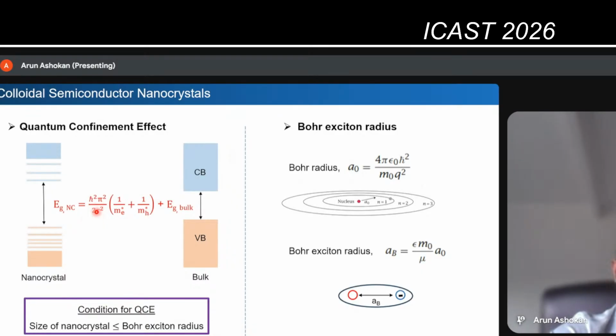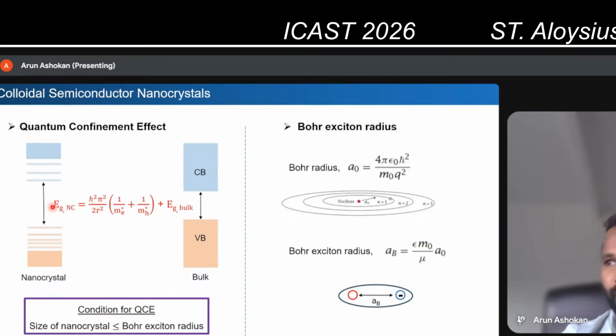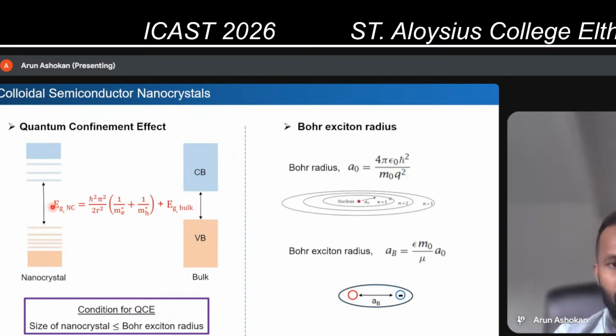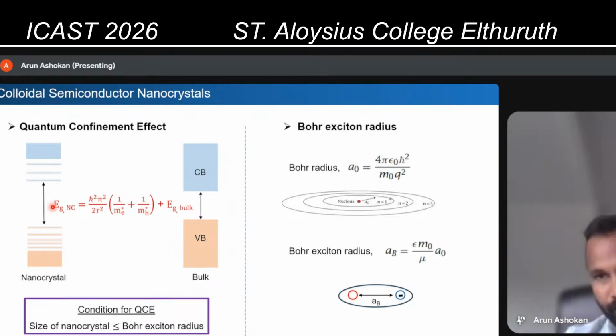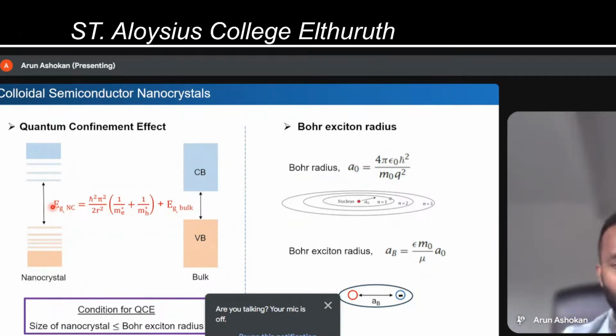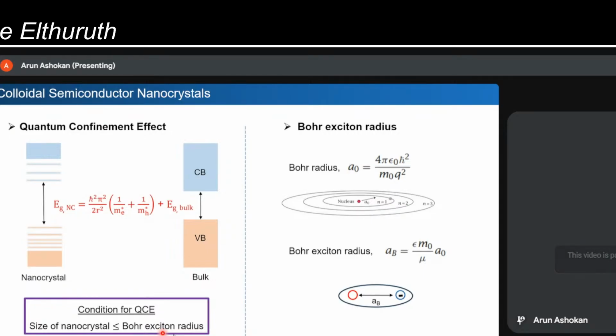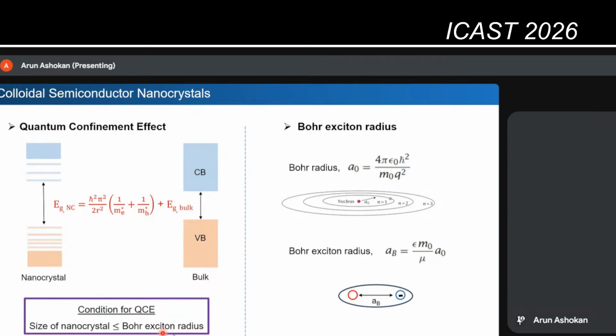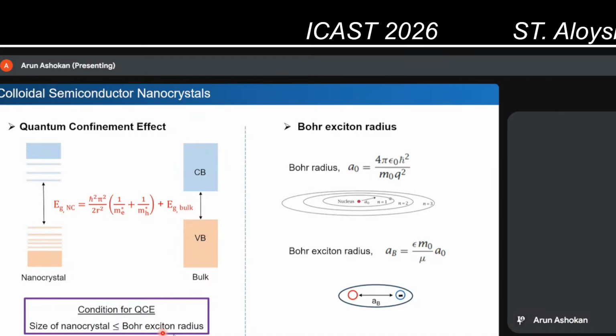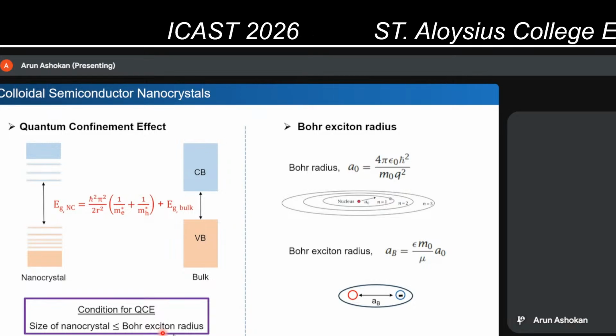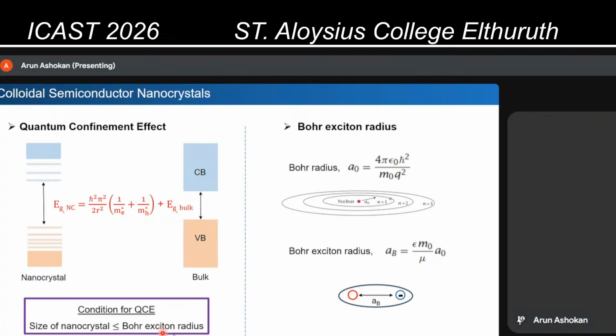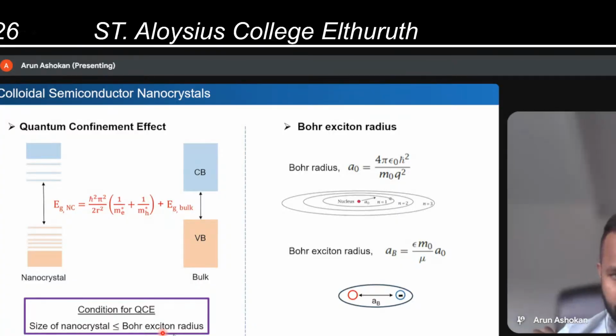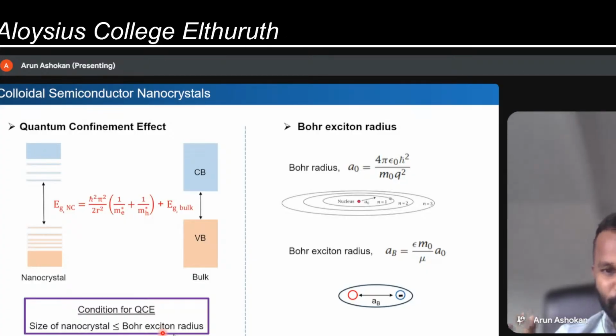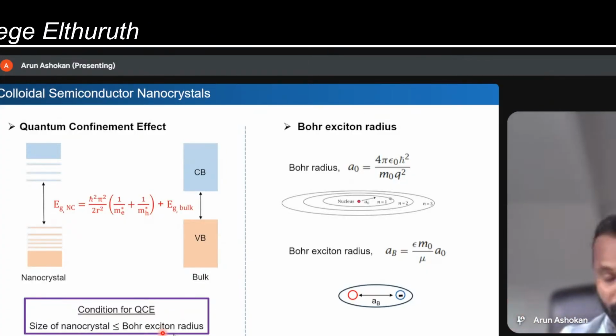Basically, the radius of your particle, the size of your particle, is inversely proportional to the band gap. So basically, when you reduce the size of your nanocrystals, your band gap increases. And this is called quantum confinement effect. And there is a condition for exhibiting quantum confinement effect. The size of the nanocrystal should be less than what's called a Bohr exciton radius. We all are familiar with what Bohr radius is. Bohr radius is basically the most probable distance between a nucleus and the electron. But Bohr exciton radius is something similar, but in place of the nucleus, it's the hole. So basically, the distance between hole and an electron is called Bohr exciton radius. So when the size of the nanocrystal is less than or equal to your Bohr exciton radius, you will see the increase in the band gap, and this is called quantum confinement effect.